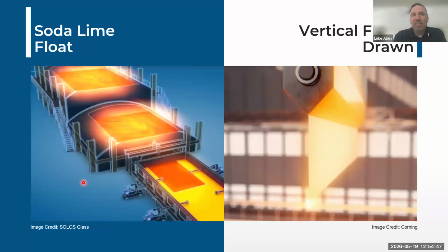It's made in a different process. You have your typical soda lime float process; this is a vertical fusion drawn process. Corning is the primary supplier of this, but it's a stories-high glass waterfall, for lack of a better word. As it moves down, it actually cures, and then the pieces are cut off, and you can get 50, 60, 70 square foot sheets of the thin glass. So very versatile. You've got a really larger area that you can work with when comparing to VIGs or aerogels.